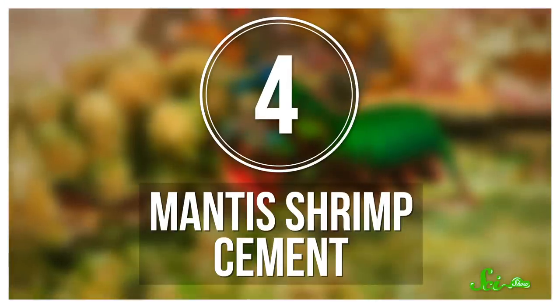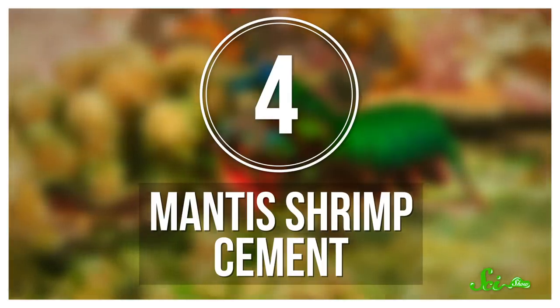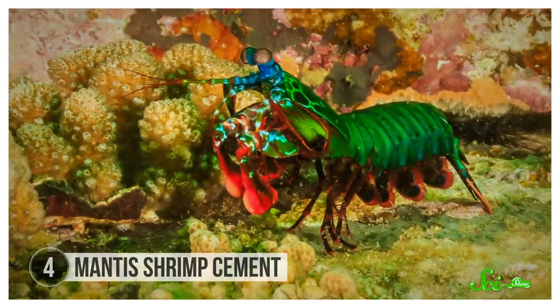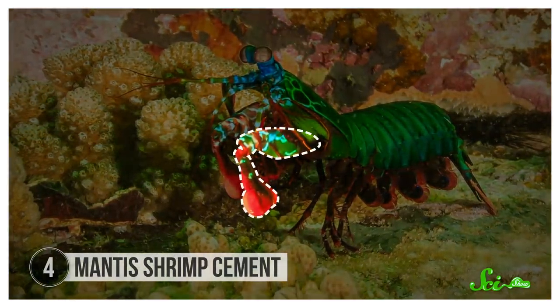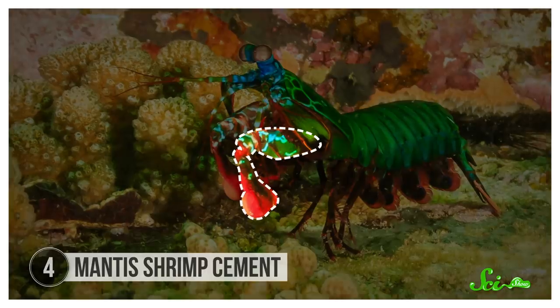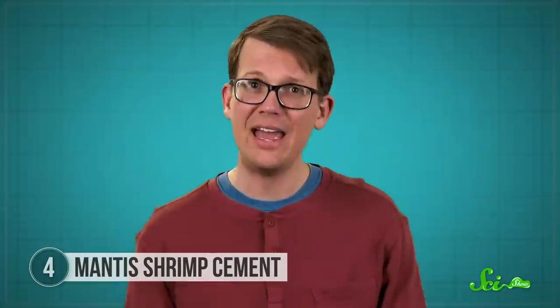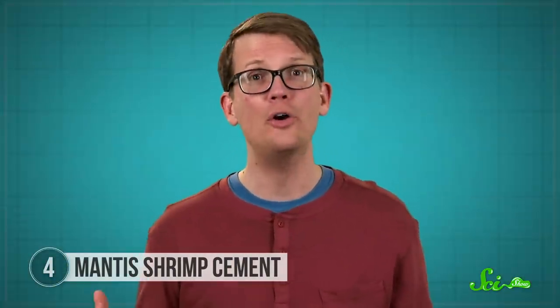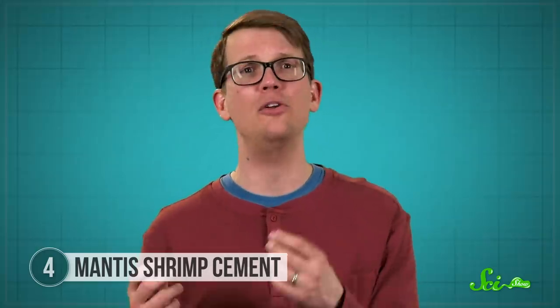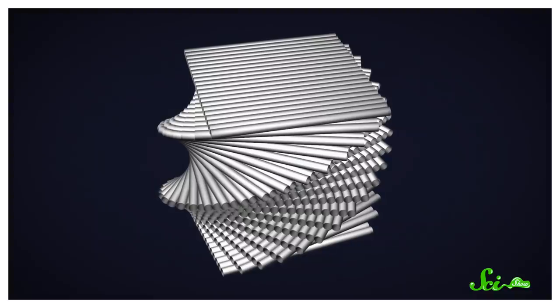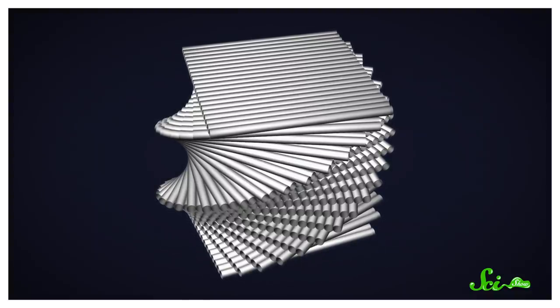More specifically, in 2018, they developed 3D printed cement structures inspired by the mantis shrimp. Mantis shrimp hit their prey with a club-like front claw at an extremely high speed, which generates a lot of force. But even then, that claw does not crumble under pressure thanks to the way the shell's microscopic layers are arranged. The layers are stacked in a spiral, each layer slightly offset from the next.